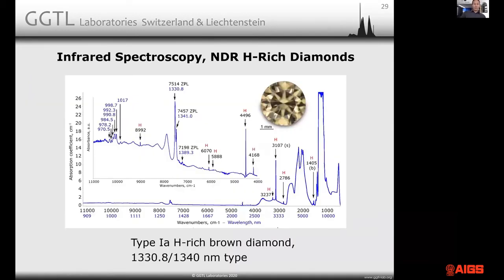Very interesting is the infrared spectroscopy. Now in the infrared spectroscopy, we have always seen that they're rich in hydrogen. So we have those sharp peaks at 3107, 1405, all the overtones and combinations that you can find. And always there was a broad band at around 7,500 wave numbers. There was some funny broad band in certain hydrogen-rich stones.